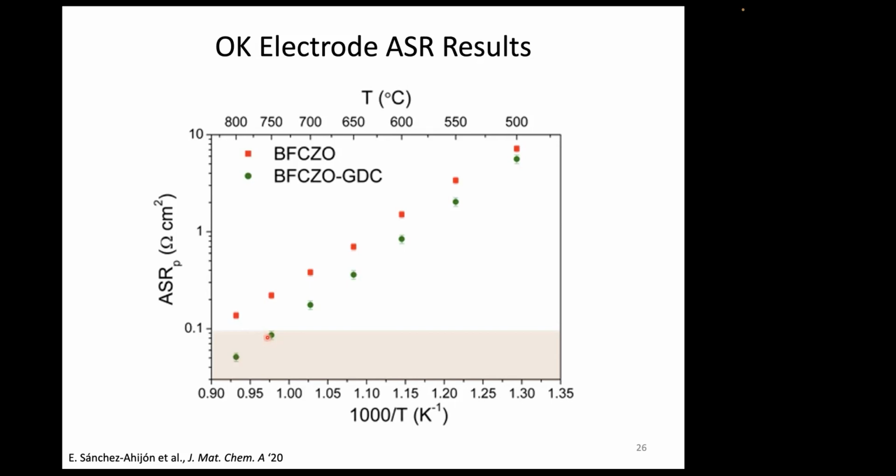However, that puts us essentially on par with existing commercial materials, which isn't going to cause anyone to look seriously at modifying their fuel cells because it's not dramatically better. But we realized that a lot of our resistance was coming not from our oxygen exchange, which we had well optimized, but from electrical resistance. You can remember our screening for electrical resistance was not very clever. It was based just on band gap.